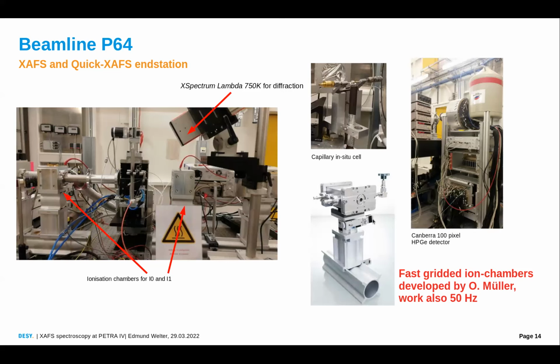P64 is also equipped with special gridded ionization chambers, which are fast enough to measure XAFS and especially the XANES of the XAFS with up to 50 Hertz.